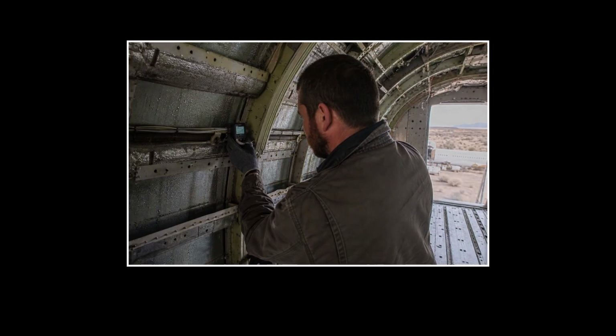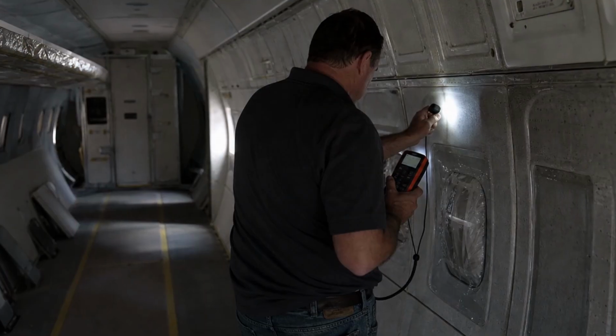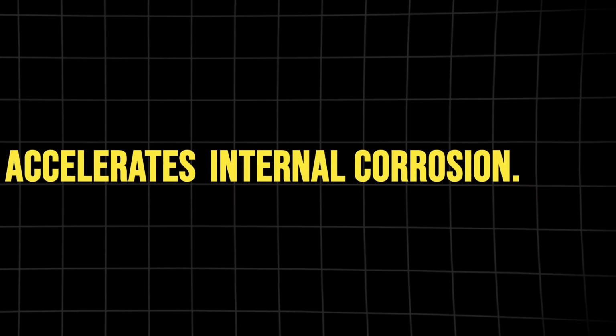Desert temperatures swing dramatically between day and night, and that cycling causes moisture to condense on the interior walls of the fuselage. A fully sealed aircraft traps that moisture inside, creating a humid microclimate in an aluminum tube, exactly the conditions that accelerate corrosion from the inside out.